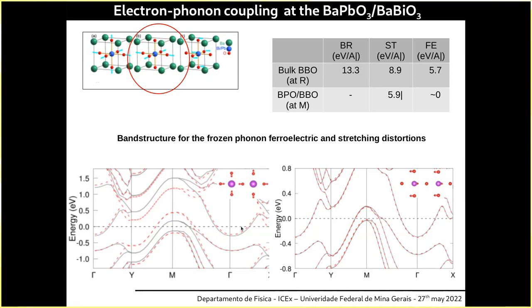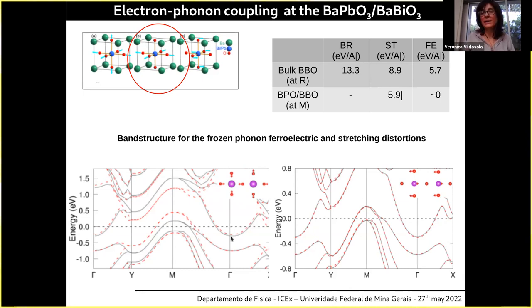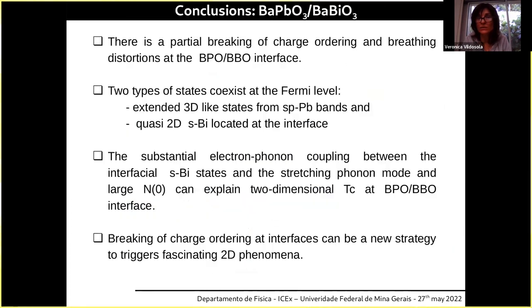If we would manage to induce some breaking of charge ordering so that also the bismuth 5+ would be involved, because you see here, these are the unoccupied bismuth 5+, and they do couple to the stretching mode. There is a big shift to the stretching mode, but they are empty. If we would manage to induce a breaking of translational symmetry so that they can also participate in the metallic state, the electron-phonon coupling would double, and the critical temperature would be much larger. This is what we predict.